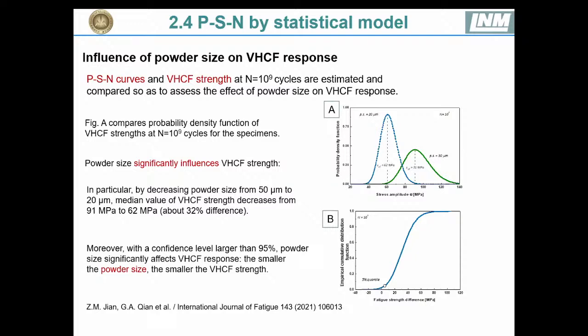And using this method, the PSN curve, we can also estimate the fatigue strength when the fatigue life equals 10 to the 9th loading cycles. And here we can see the distribution of the fatigue strength for the two printing powder sizes.